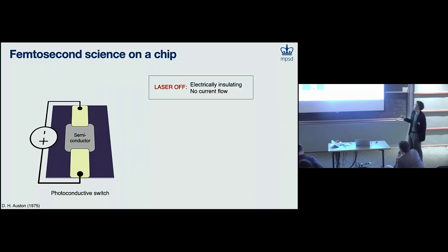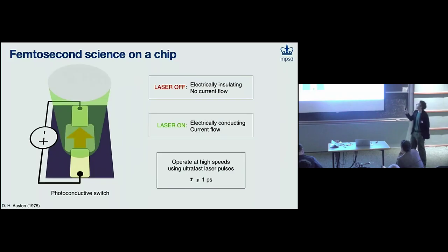And what this consists of is an insulating semiconductor patch. If you were to slap some electrodes on this and apply a DC voltage bias, nothing happens. But if you now shine laser light on this patch that's resonant to the band gap of the semiconductor, you create electron-hole pairs, and then in the presence of this DC bias, a photocurrent will flow across the switch. And it turns out that you can operate these switches at very high speeds when using ultra-fast laser pulses, where the time scale is basically set by the carrier relaxation time in your semiconductor. So if you use a dirty semiconductor like amorphous silicon, which is what we use, we can routinely get sub-picosecond current pulses across these junctions.